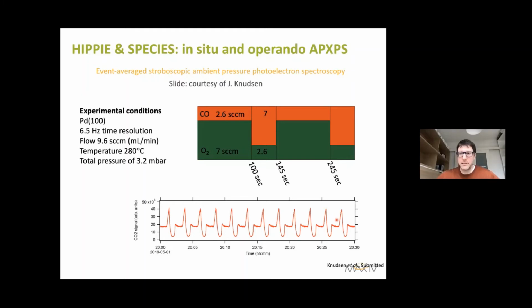But again, it's the same type of experiment. You pulse gases. You have one composition, the CO-rich gas composition here, and then you switch to the oxygen-rich, and you try to see the surface composition and correlate it with the gas composition in the pulse, in the other pulse, and in between.